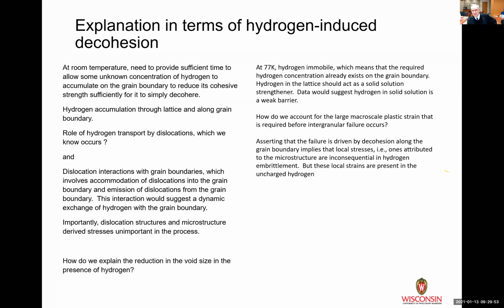The challenge with that mechanism, though, if you've ever looked, and I didn't show you this evening, but if you look at dislocations hitting a grain boundary, they'll go into the boundary, but the grain boundary will also emit dislocations. If that happens, the dislocations go in, bring in hydrogen. The dislocations going out, they take away hydrogen. So remember, one of the things I asked you to think about is that if we're going to make the assumption that it's just straight hydrogen concentration in the boundary that causes decohesion, can we make the assumption, or is it right for us to make the assumption, that the hydrogen concentration is static while you've got plastic processes? And I would say, at least in the early stages of straining, that can't be true because dislocations do move hydrogen. So now we've gone from a static hydrogen concentration on the boundary to a dynamic one.